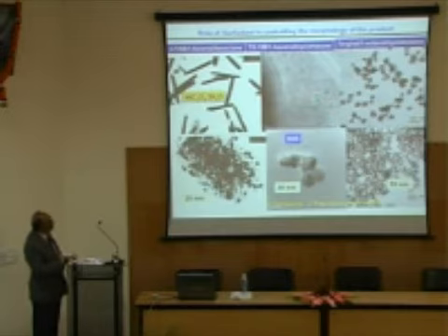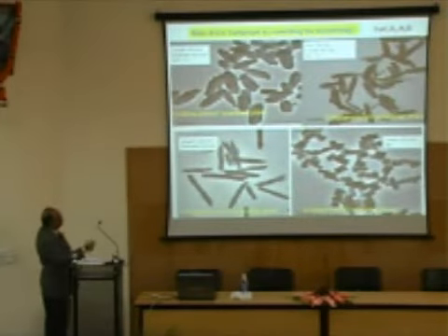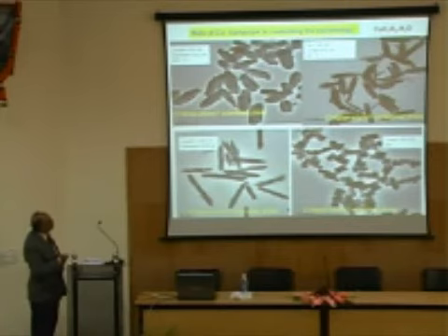Of course, these are very smooth rods. This is again to show another role of another chemical. I didn't get into that. It's called a co-surfactant. If you modify the co-surfactant also, you can modify the width of the rod. Here you can see the aspect ratio is larger than this. Here the length and breadth are becoming nearly equal.